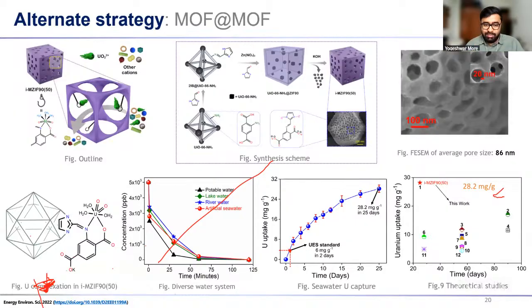And then we did all the studies like artificial seawater, river water, lake water, potable water, like all the water systems. In my case, within 120 minutes of studies, it absorbs nearly 99%, and it reaches the UES standard in only 2 days. Earlier MOFs were reaching the UES standard in 16 days, right? The standard limit is 30 days. But this, since it is highly macroporous and has a very particular interaction site or ligating site, does this job in only 2 days. Only 2 days. And that is the best achievement.